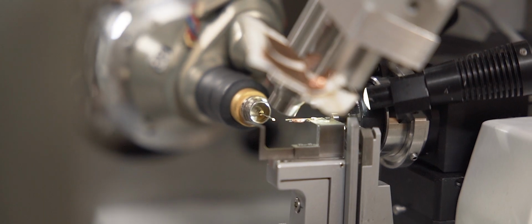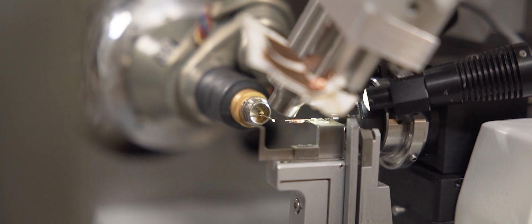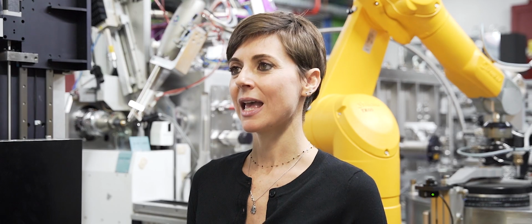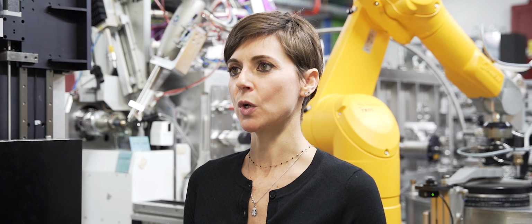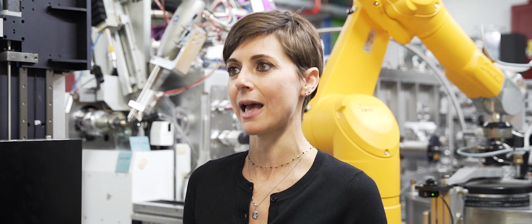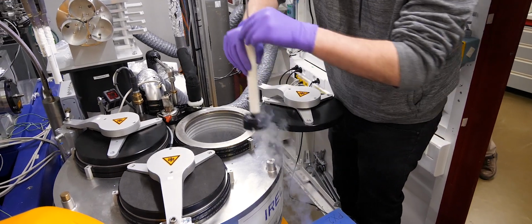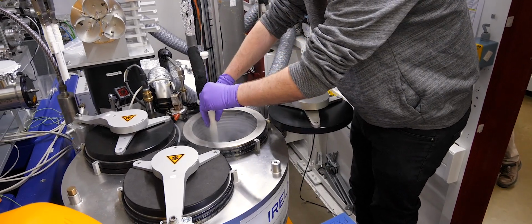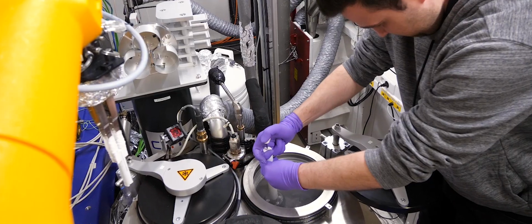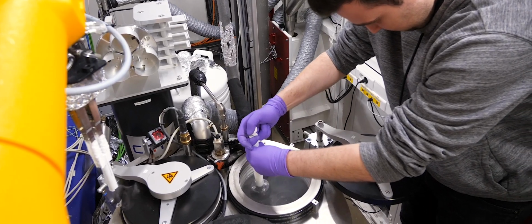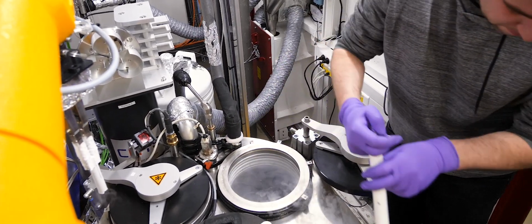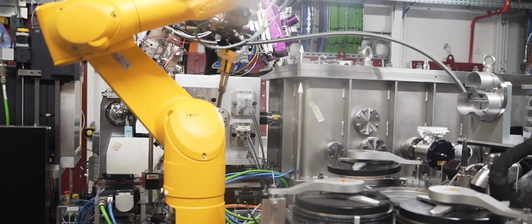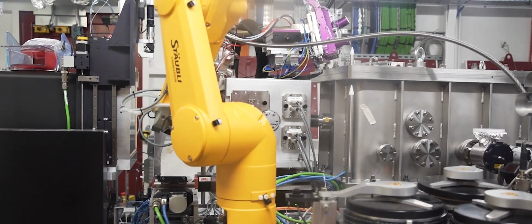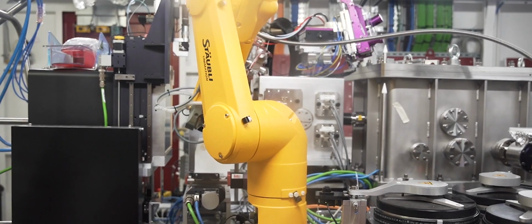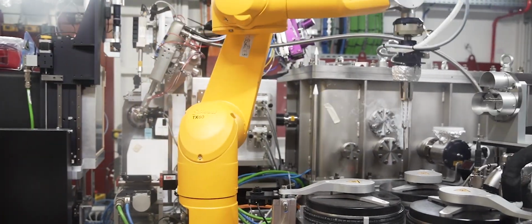The goniometer is equipped with multiple high-performance rotation axes, sub-micron resolution centering stages, and an on-axis microscope, which allows us to see the sample as the X-ray beam does. The robotic sample changer automatically transfers samples mounted on spine pins from the dewar to the goniometer. The dewar can hold 9 unipucks for a total of 144 spine pins. The time to mount and unmount between two samples is less than 30 seconds.